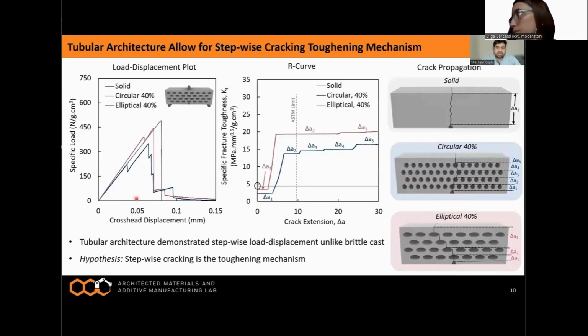The R-curve shows that the toughness of the tubular architected material increased with the extension of the crack in a stepwise manner. This increase is directly correlated with the load displacement plot, where the softening corresponds to the crack extension and the hardening corresponds to the steep increase in the R-curve. We hypothesize that the stepwise cracking through the tubes is the toughening mechanism which leads to an increase in toughness.